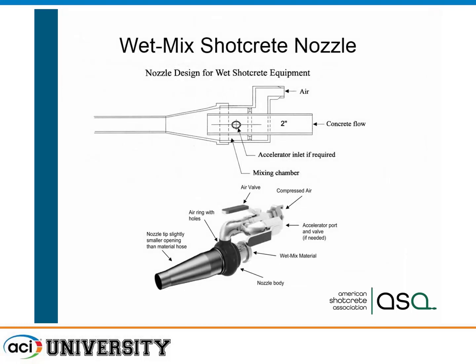Here you can see the wet mix nozzle. Basically, material comes through. It's pretty typical. Our hoses are 1.5 to 2 inches. Comes through, and then we use air to accelerate. One of the cool things about wet mix is, we can actually add a rapid set accelerator, we can get almost instant set of the material in place, and we can get very early strengths. If you added a rapid set accelerator in your ready mix truck, you wouldn't get it out of the ready mix truck. Because we can add it right at the point, immediately before placement, this allows us a lot of flexibility when we're using accelerators.